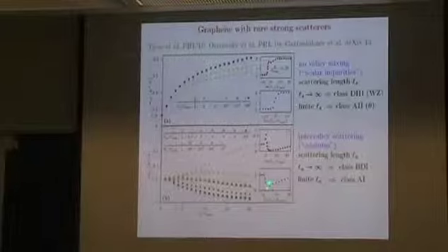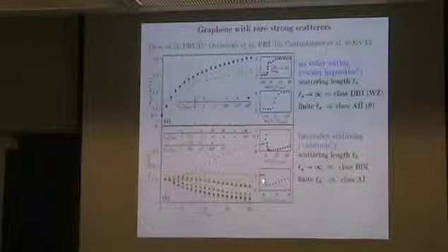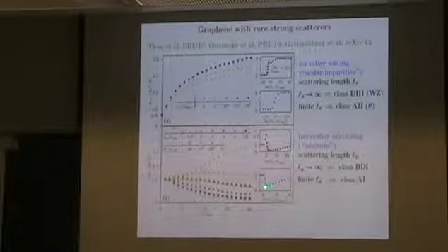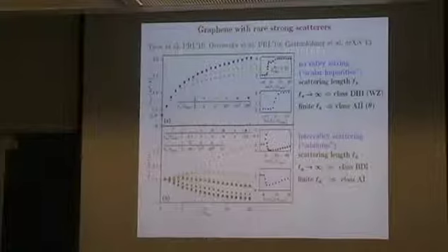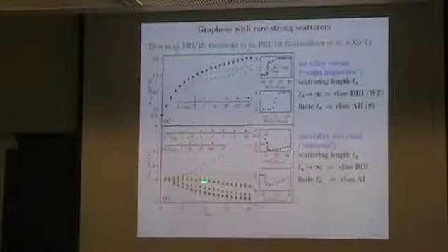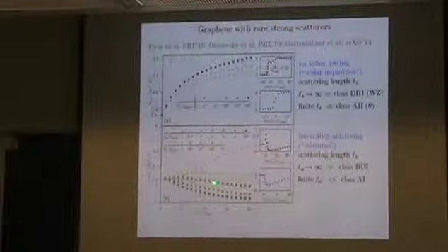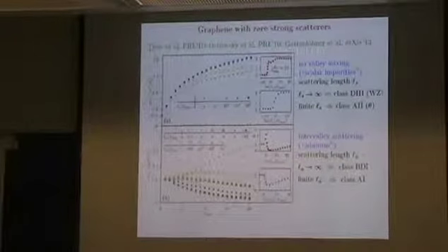So if you look at the conductivity as a function of the impurity strength, for a certain system size, it first goes down because of localization, and then when you increase impurity strength further, it returns back because you go to the chiral symmetry class. So for strong, very strong but finite impurities, we first see the behavior of this chiral class, the constant conductivity, and then there is a crossover to this normal orthogonal class. They start to see localization. So you see 4 different symmetry classes here,